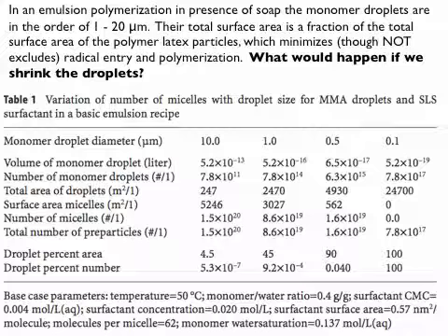So now hypothetically, what if we just lower the droplet diameter? Put a more hardcore stirrer in it, for example. Let's shrink it by a factor of 10. And you suddenly see that the total area of droplets and the surface area of the micelles start to be competitive with each other. About 45% of the total surface area is now the area of the droplets. So droplets start to compete with the micelles, which means our picture of emulsion polymerization is no longer as simple as we thought. We now have to take into account that droplets can also nucleate.